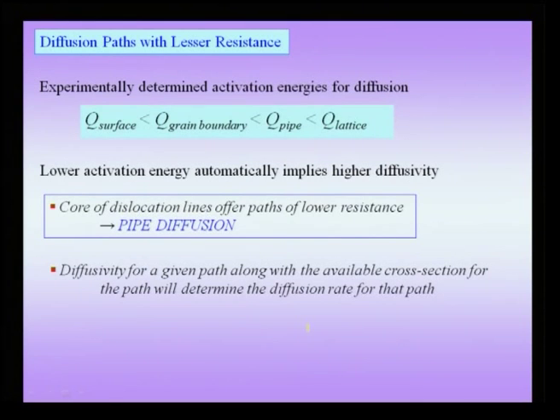This is why when trying to homogenize an alloy — for instance a casting that is inhomogeneous — the homogenizing hold must be much longer compared to, say, a carburization experiment where carbon diffuses from the surface. The diffusivity of an interstitial species is typically much higher, so to diffuse an interstitial species you carry out the diffusion anneal for a smaller time. What we have talked about so far is lattice diffusion — the species diffuses through the lattice, not through any defects in the crystal.